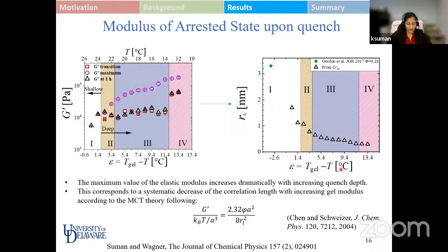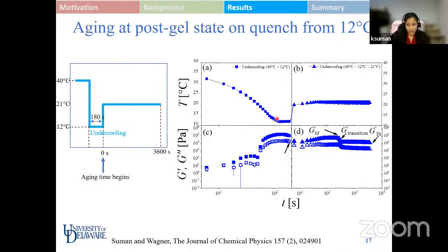As can be expected, as we go deeper and deeper into the arrested state, which is at deeper quench depths, we have lower values of localization length because the system is getting more and more arrested. The microstructure is getting more arrested over here. So with the knowledge of a bulk parameter, we are able to get insight into the microstructural localization length of the model gel.